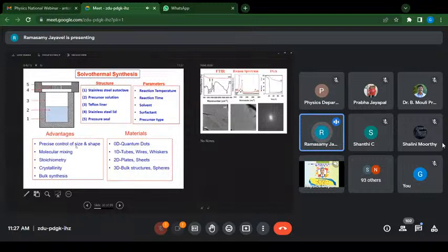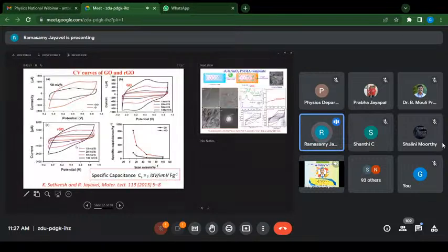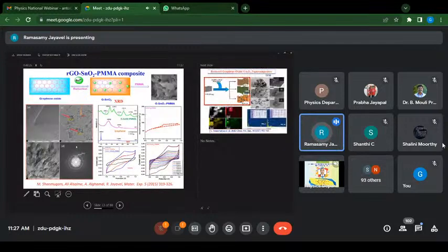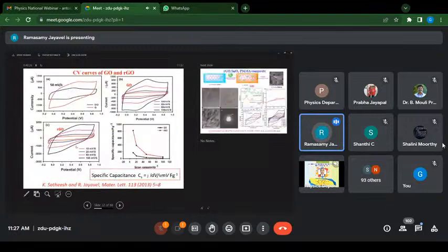So, these are all something about the material, and other parts are our research work, which may not be of very much interest for you. But we started with graphene oxide, graphene, and reduced graphene oxide, and we could achieve a specific capacitance of about 800 farad per gram, but the current was of the order of microampere. This implies that you can have very high energy density, but because the current is in the range of microampere, we cannot get power density.